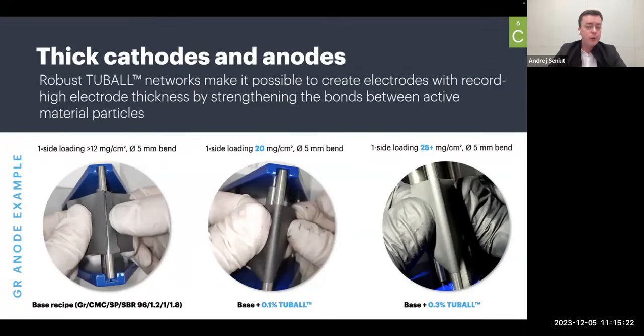This is quite fresh results, but very exciting, and these results lead to traction on the market. We see more and more projects now applying single carbon nanotubes in these kind of systems. I'm speaking about thicker cathodes and anodes. So because single carbon nanotubes improve the cohesion between the particles, between active material particles, the mechanical strength and flexibility of the electrode is improved.